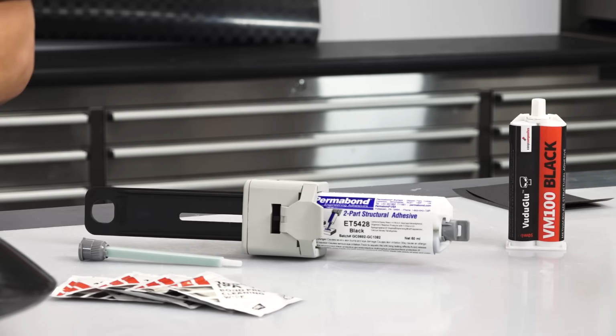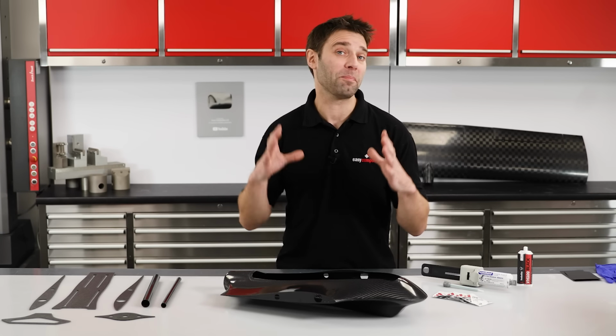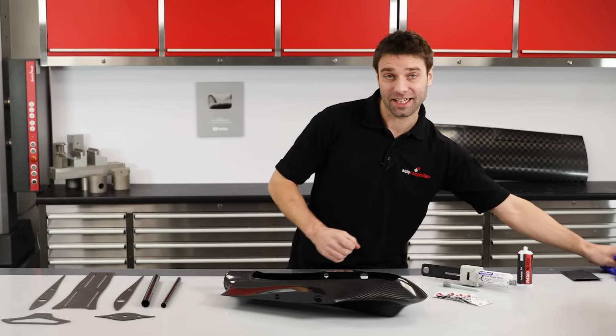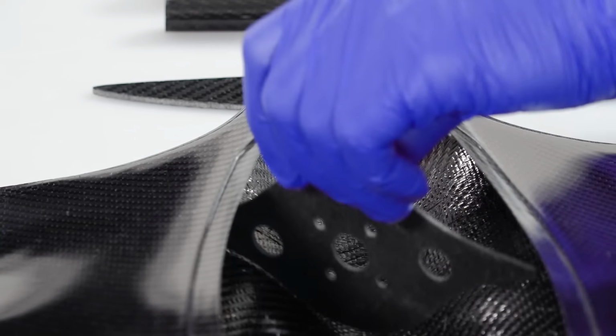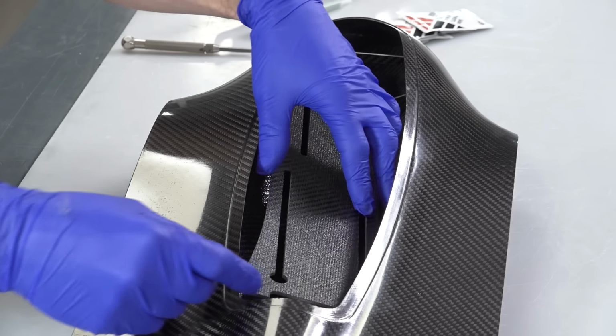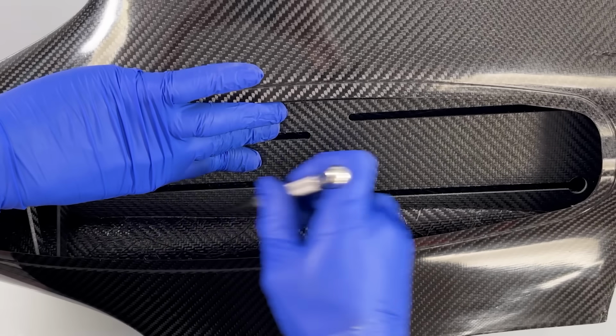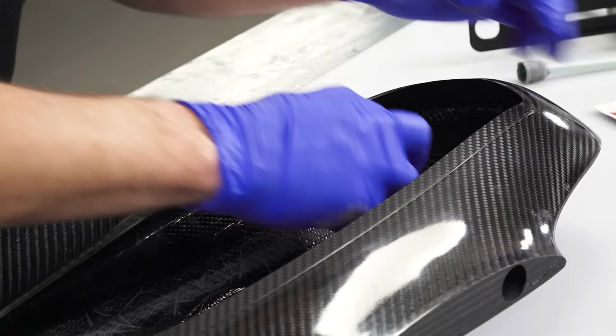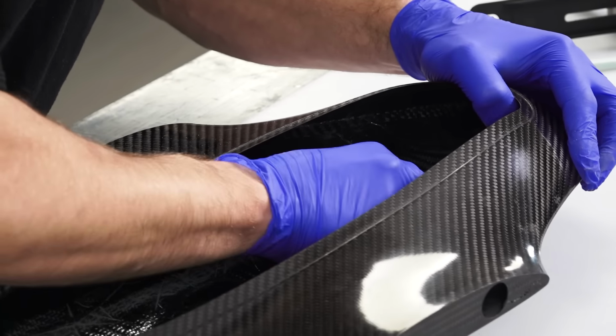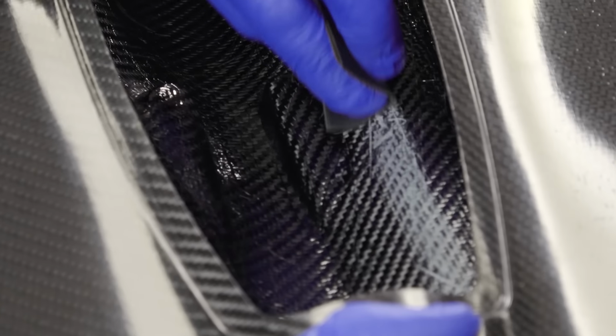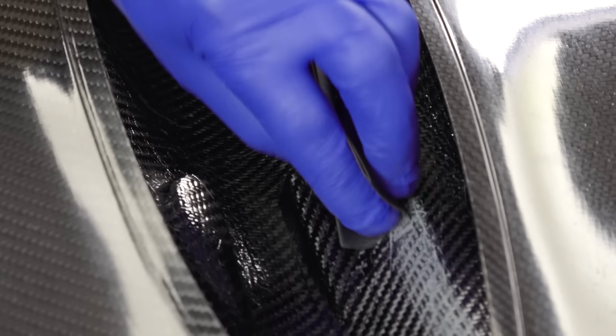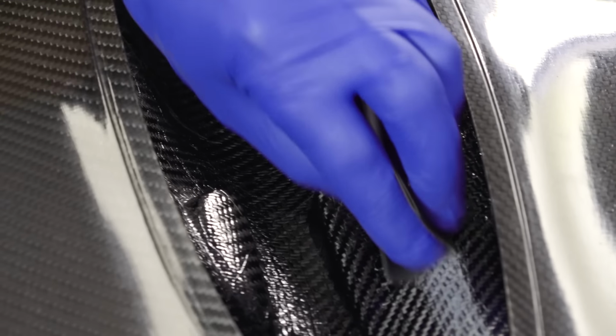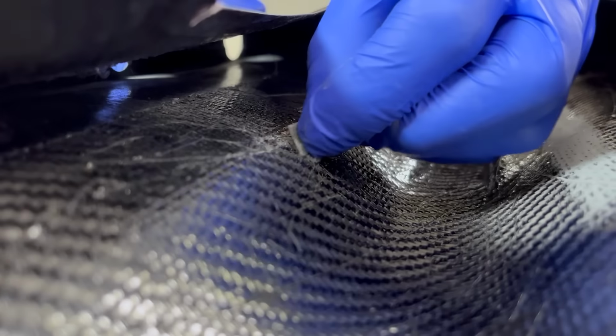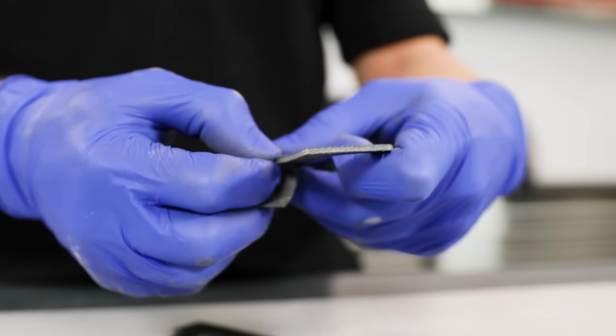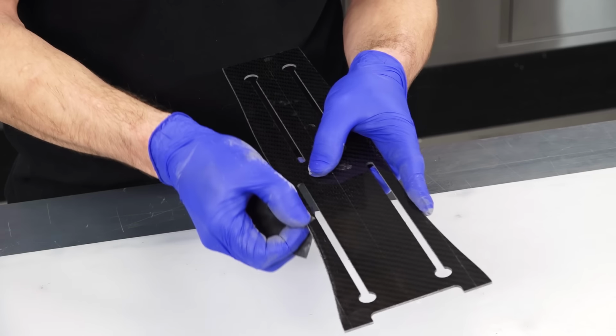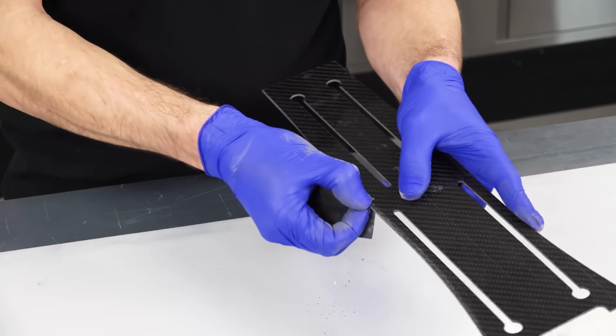The first stage of any adhesive application is to prepare your surfaces. So let's get started with that. The parts are positioned and their locations scribed on, so I know where to key. Preparation for bonding with ET5428 is the same as for most other adhesives, so that's a case of keying the surfaces to be bonded with abrasive paper. Peel-ply surfaces wouldn't need keying, but these being straight from the release film, they will do.